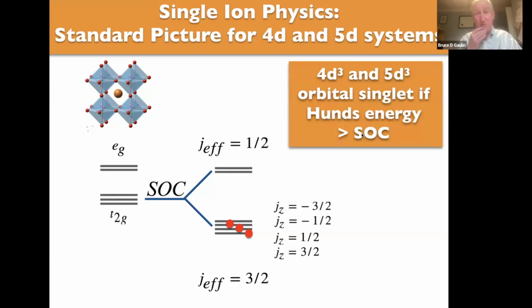And actually, what you would expect would be very conventional physics, where there'd be some Heisenberg type interaction, and it would order into a simple structure and give you spin waves that have no gap, because it's a Heisenberg type interaction, at least to the extent that you don't mix in the upper level EG.